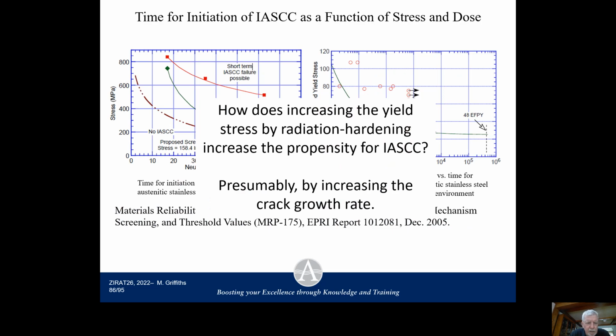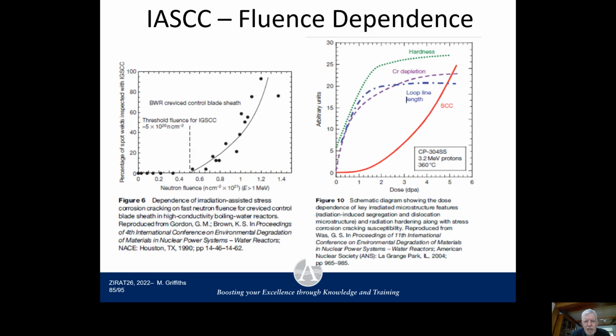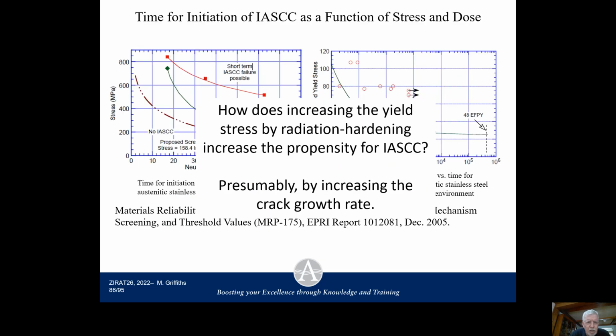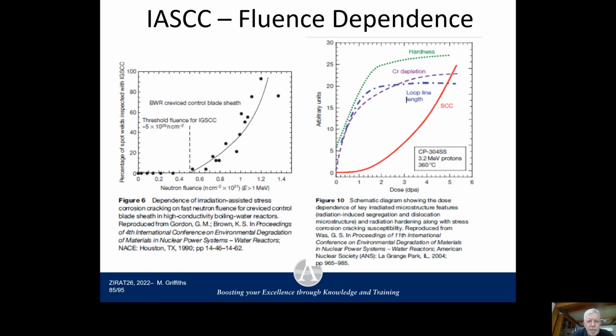So put this together. Here's a summary from this report, the EPRI report. If we think about the initiation of stress corrosion cracking, so bearing in mind that this is the propensity for seeing cracking, how often you see it in welds. Let's look at the initiation. From an initiation point of view, there's an indication that higher stresses increase the initiation. So it reduces the dose or the time one needs to initiate cracking, and that would be similar to this hardening effect.